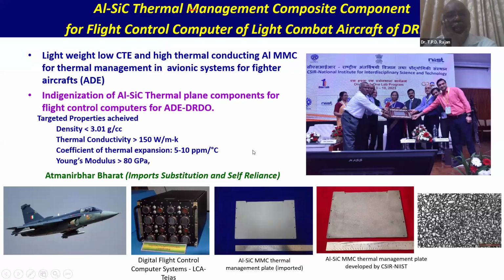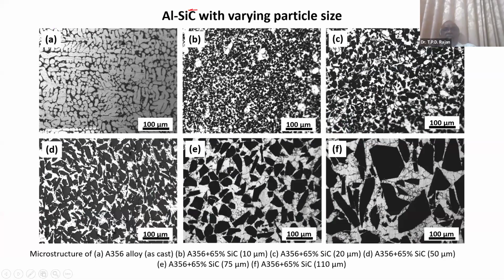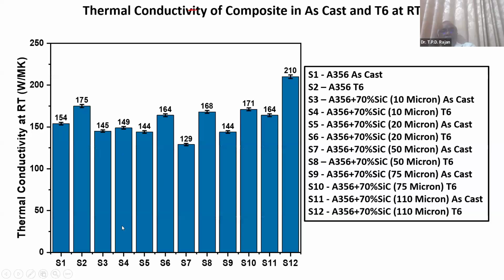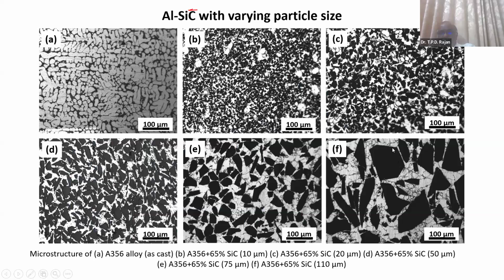So this I think I had shown you earlier. You can see the impact of the particle size. Here we changed the particle size of silicon carbide and evaluated the thermal conductivity. We found that the finer the particle size, the lower the thermal conductivity. We changed the particles from 10, 20, 50, 75 and 110 micrometer, and 110 shows high thermal conductivity. Here we have two materials: one is the aluminum alloy and the other is silicon carbide particles.